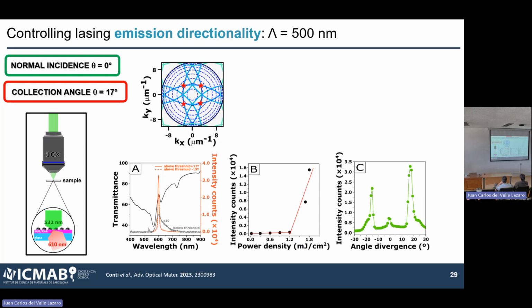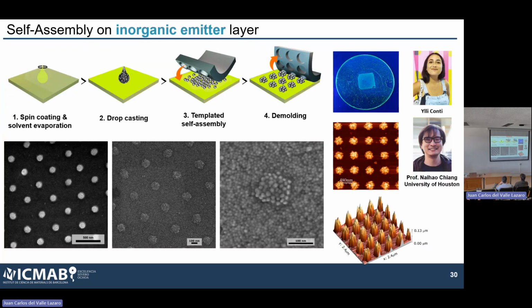And so Ili joined a 4-month research stay in the group of Professor Nalhao Chiang in Houston. The idea was to move from rhodamine B, a molecular system we thought to reach quite easily, to quantum dots, hoping to not only have a more stable system, but also to target two-photon emission systems. So in this case, instead of pumping the system with a 532 laser, the idea was to pump it with a near-infrared laser and have two photons combining to promote the emission.